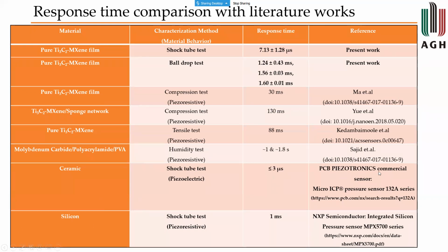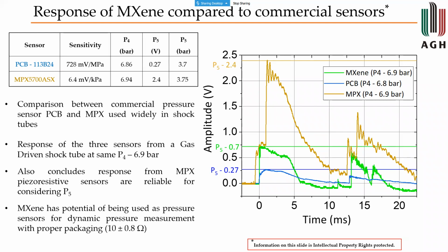So this was the initial stage of comparison we started off with, the specifications that we have from commercial sensors. The PCB Piezotronics commercial sensor is basically a ceramic PZT type sensor that is piezoelectric in nature, and the next one is the piezoresistive, silicon on insulator type of sensor, which is also used in the same shock tube for calibration. We did find that the performance of the response times were really good, and we also found the response signals to be quite promising when compared to the PCB sensor, where the one on the top, the blue one, is from the piezoelectric sensor that is used in the same test setup, and the one from the piezoresistive is also given.